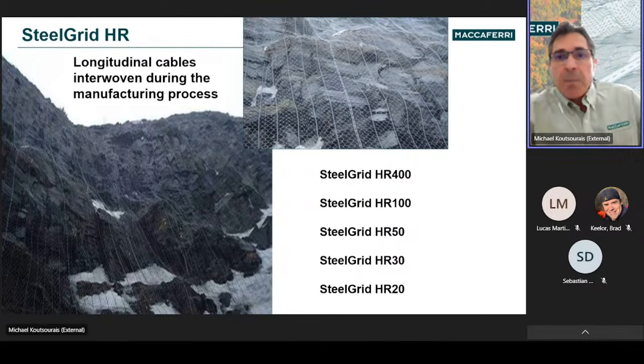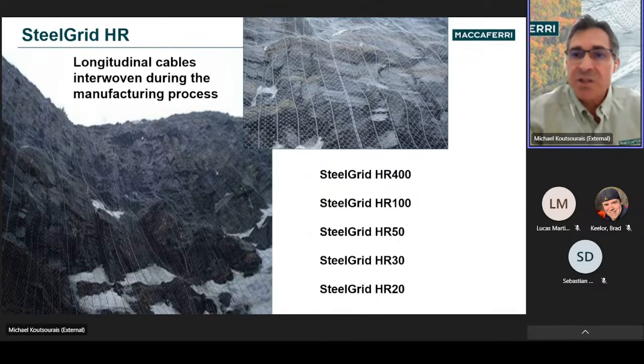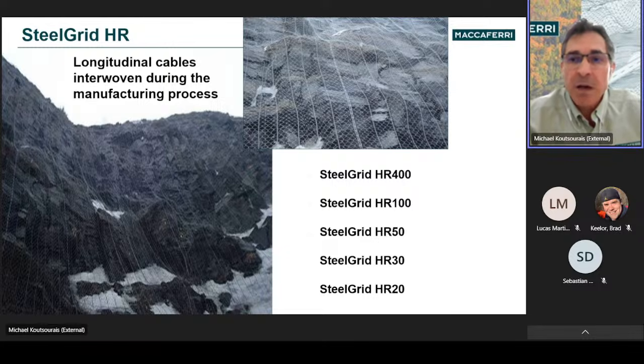Maccaferri manufactures a composite cabled mesh, which consists of a double-twisted steel wire mesh and high tensile strength steel cables, which are woven under tension into the mesh during the manufacturing process. The pre-tensioned high-strength steel cables result in ultimate strengths that are mobilized at only 6% strain. The lower elongation under load results in less loading on the drapery system.